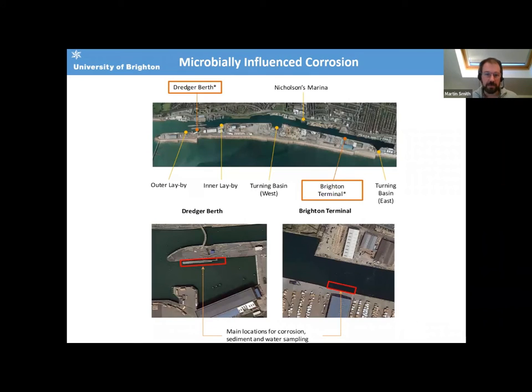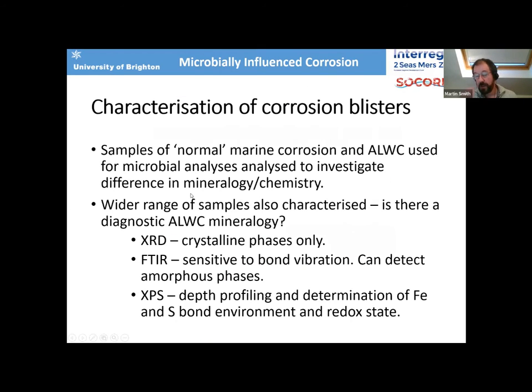So this was our initial sampling points, Shoreham Harbour in the UK. We've got within the main harbour where we've got a fixed water level by lock gates. We don't get tidal variation. And a main study site, the dredger berth here, which is tidal. The approach to actually characterising those corrosion blisters, we sampled both what appears to be normal marine corrosion, and I'll get on for a moment the fact that it's actually very difficult to identify in this particular site something that isn't influenced by bacteria. And we coupled microbial analyses with mineralogy and chemistry. And the approach took in X-ray diffraction, Fourier transform infrared spectroscopy, and X-ray photoelectron spectroscopy. So we're going from quite high-end research techniques through to things that we can hopefully apply very cheaply and convert to in-situ analysis techniques that might assist in early recognition, remediation, and prevention.